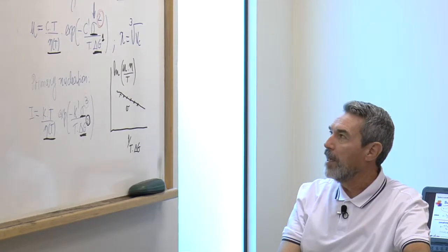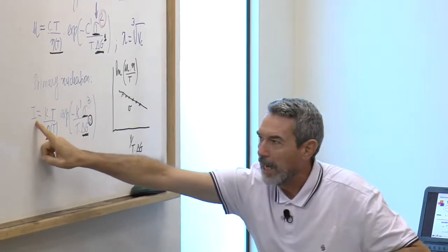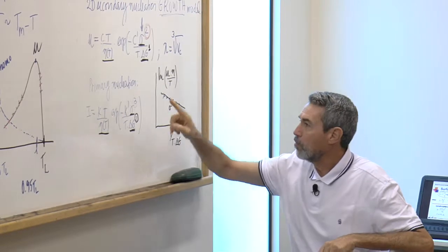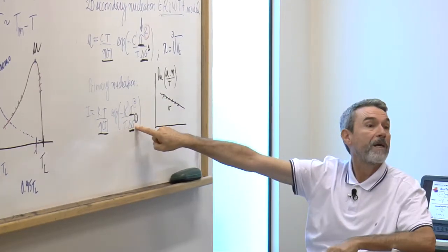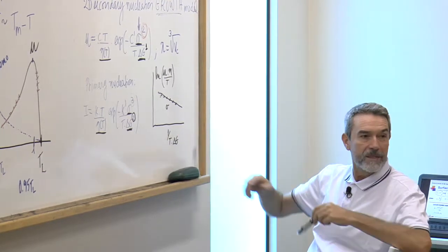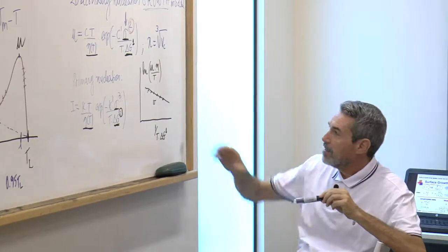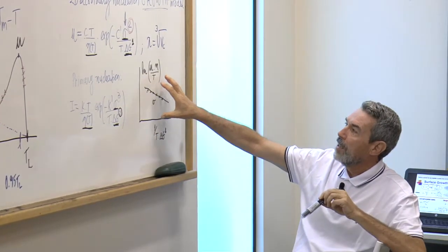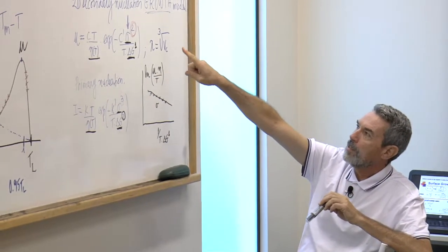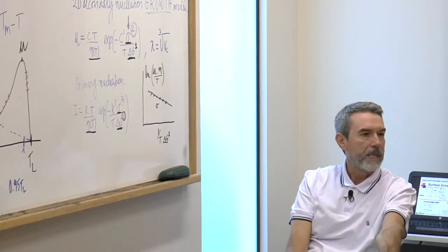For primary nucleation, you have plotted I times eta divided by T versus 1 over T delta G square. Now it's delta G, not square here. Delta G to the power 1. This is the test that you can do to check whether the 2D secondary nucleation growth model describes your data.